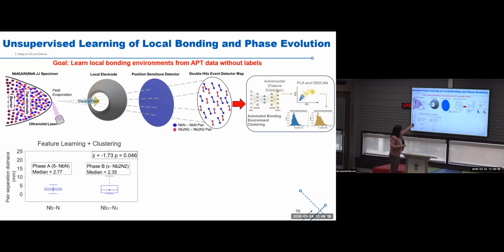And we cannot have these values exact as the crystal structure, because in APT there is a magnification effect. We have a sample, we have a detector, so there is a lengthwise misconception. So we cannot have the exact value. However, we can have the relative value. So we knew for the delta NbN phase, we have a higher d value than phase B, and that's exactly what we are seeing. Now, where they are, when I say locally, right?